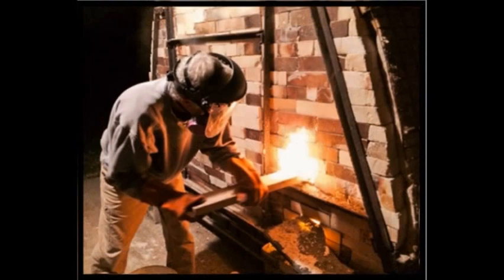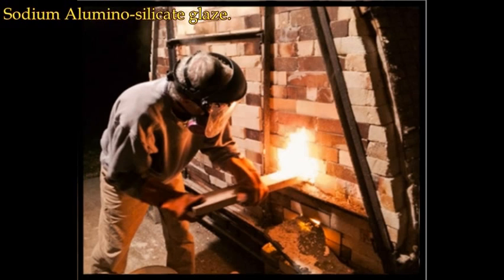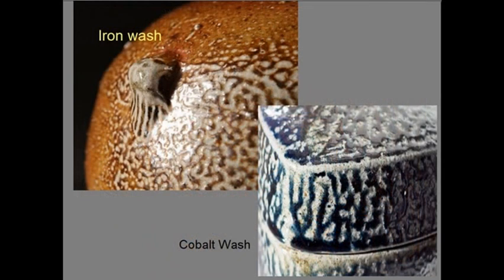Salt glazing occurs when common salt is introduced to the kiln during the final stages of the firing process. The high temperatures cause the salt to volatilize, depositing it on the surface of the ware to react with the body to form a sodium aluminosilicate glaze. 15th century Rhineland potters found that the technique produced an orange peel-like translucent coating, as seen here. Various colors are achieved by a wash of an oxide on the pot before the salt glazing is done.